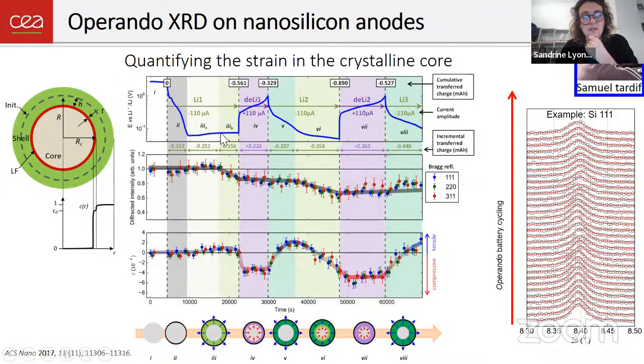And what we got as results is synthesized in this graph, where you have here the electrochemical sequence. So basically you partially lithiate and then you delithiate, and then you start again partially lithiating and then you delithiate again. So you have an electrochemical sequence that we have designed to produce the core-shell mechanism. We're looking at the intensities and we see that it's decreasing, which means you're gradually amorphizing the material. That's what you expect. And the interesting result is here.